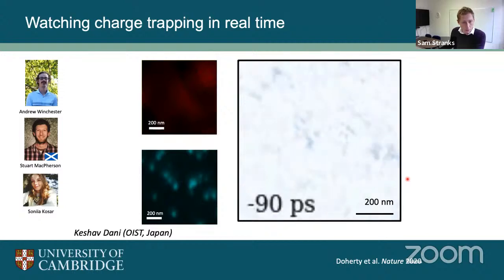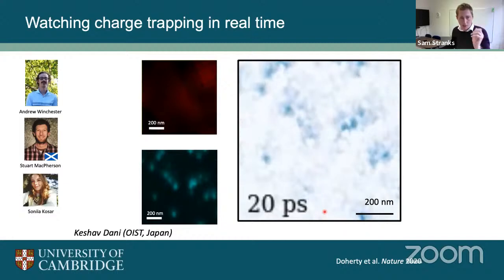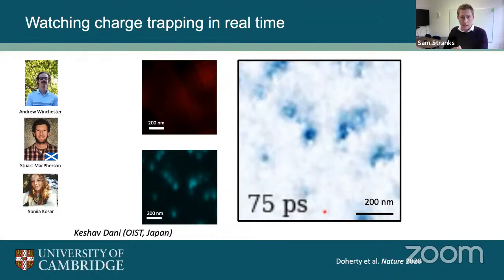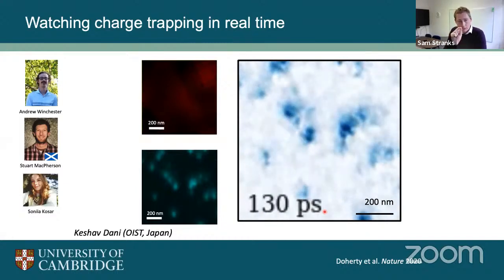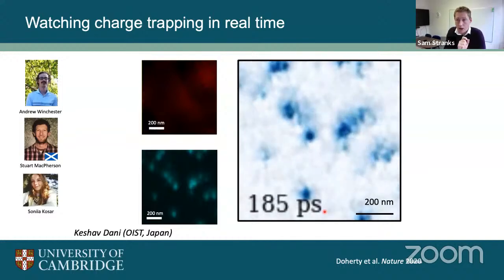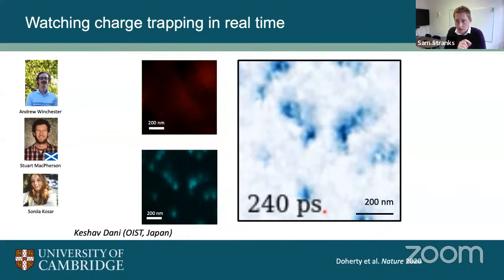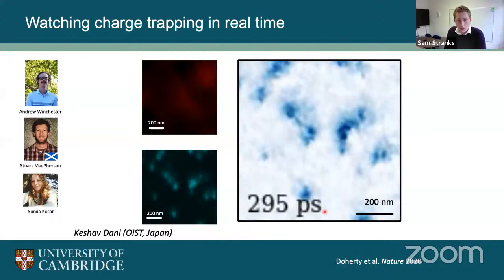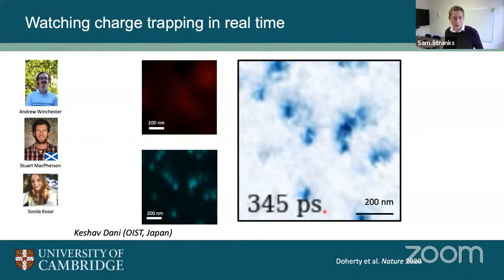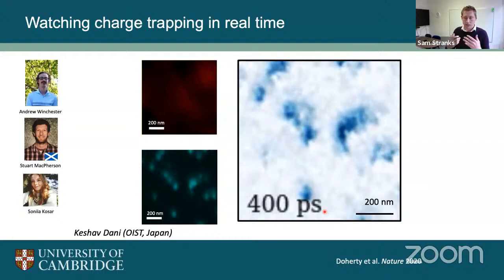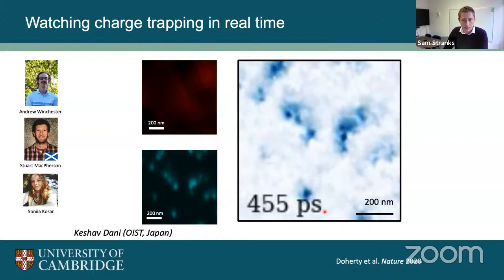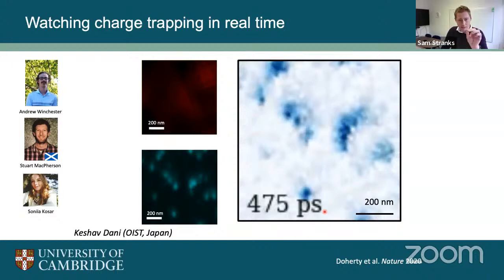And so I'm going to play a movie. This is in picoseconds, so really, really fast timescales. At 0 picoseconds, the light comes in and excites these carriers. And what you're seeing in the dark regions here are the carriers trapping in the material. These are traps where they're losing their energy to heat. And so this is a really powerful technique to delve into the nanoscale and see where these materials are losing their power. What it tells us is that we need to remove these sites where you have these dark regions.